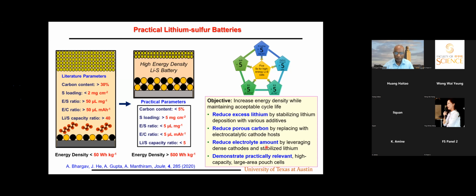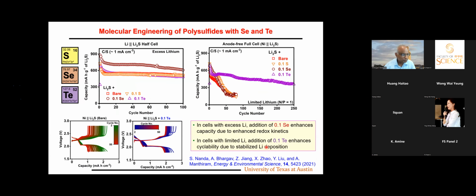And more importantly, the performance has to be demonstrated with pouch cells with reasonable loading rather than with coin cells, because coin cell performance can be very deceptive in the case of lithium-sulfur batteries. So with that, because we won't have too much time, I will eliminate a lot of slides.